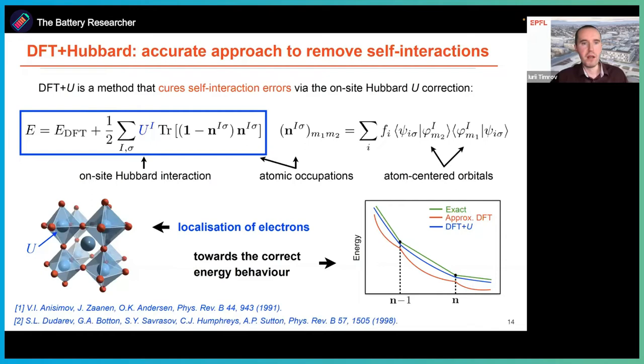Thanks to this correction, we are now able to localize electrons. If you remember, I said before that in approximate DFT the electron wants to delocalize all over the simulation cell. With this simple corrective term, we are able to really localize electrons on irons, for example. This is so because we are going towards the piecewise linear behavior of the energy. So we are restoring the so-called piecewise linearity of the total energy.